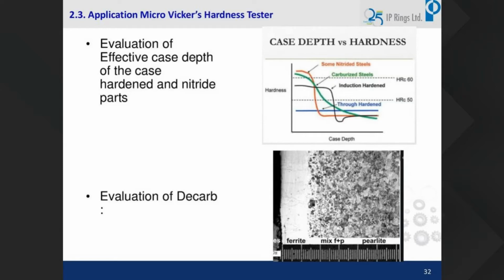But sometimes there is a partial decarb. There's a method called the traverse method. We do indentation from the surface up to a certain depth and in the core. Up to where there's a hardness difference between the core and the surface, to that extent the decarb has happened. So that is one way of correcting our furnace.